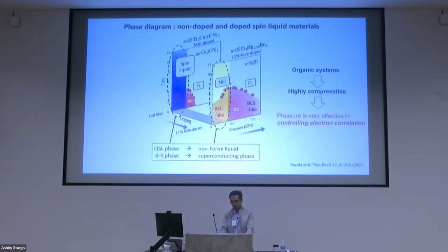This is a phase diagram of two materials. This is the doped material, and this is the spin liquid material. These are half-filled systems at low pressures. This state is a more insulating state that may cause the quantum spin liquid, I think, and then the superconductivity appears, as I said just before. And the present system, the 11% hole-doped system, shows this cross phase diagram. But in this system, the more insulating phase is replaced by a metallic one because the 11% hole doping gives rise to good metallicity.